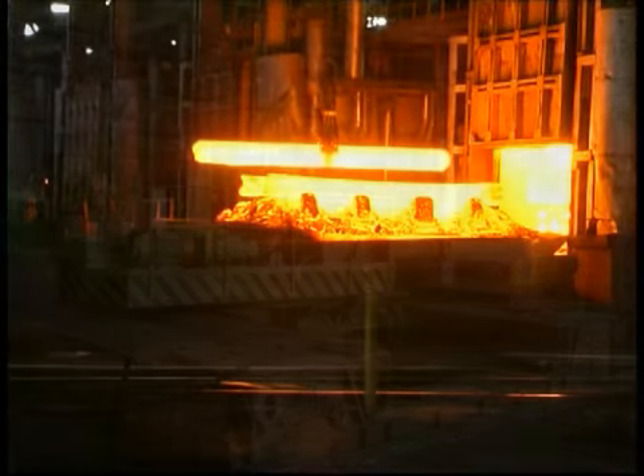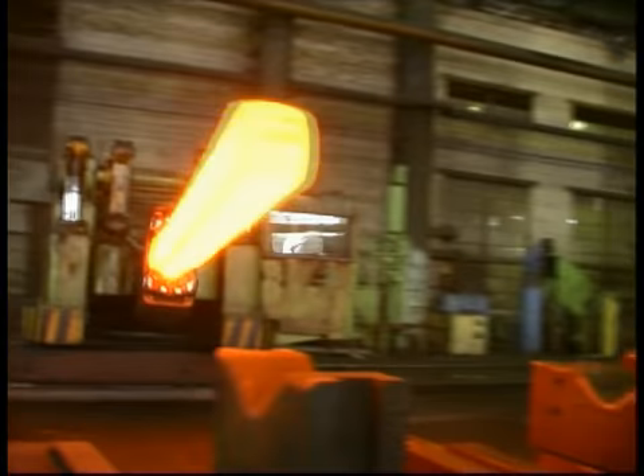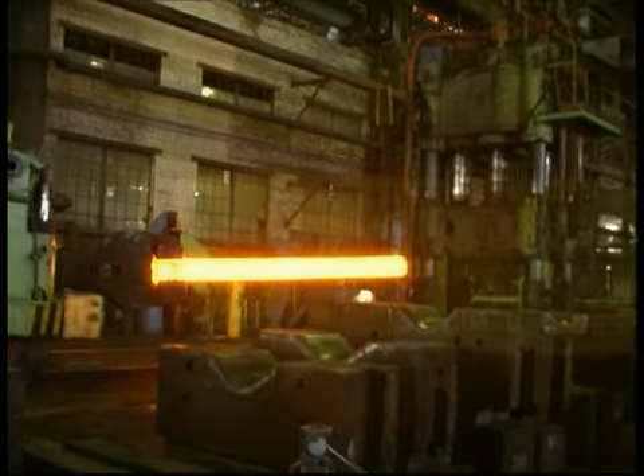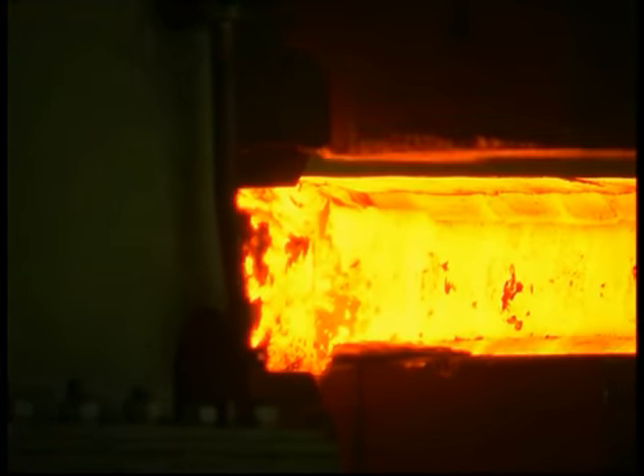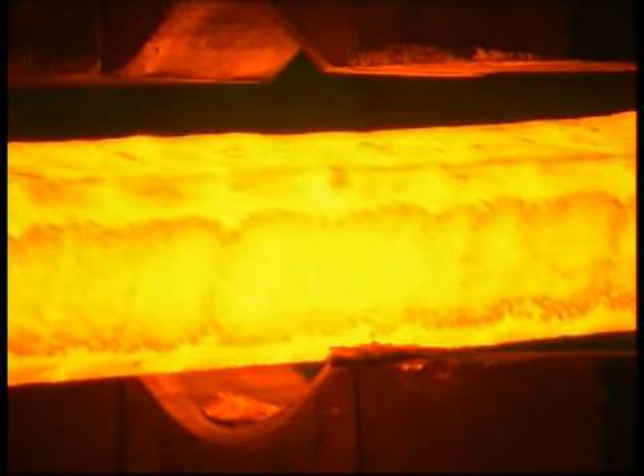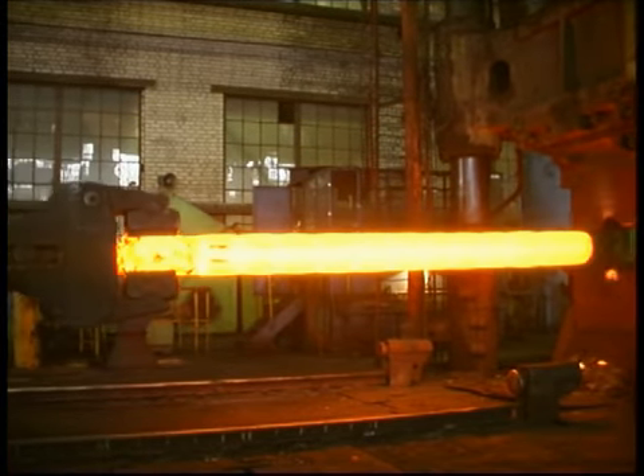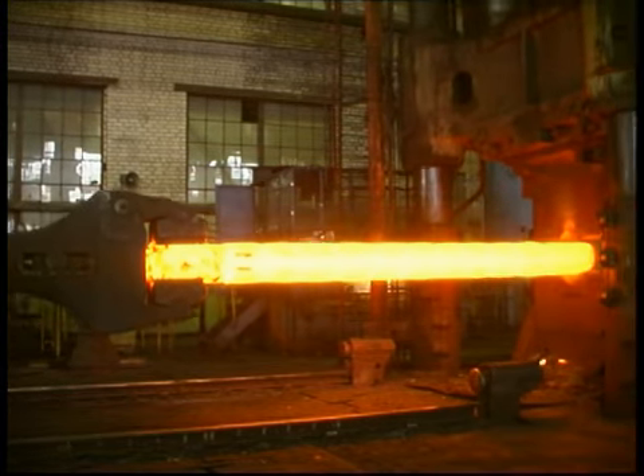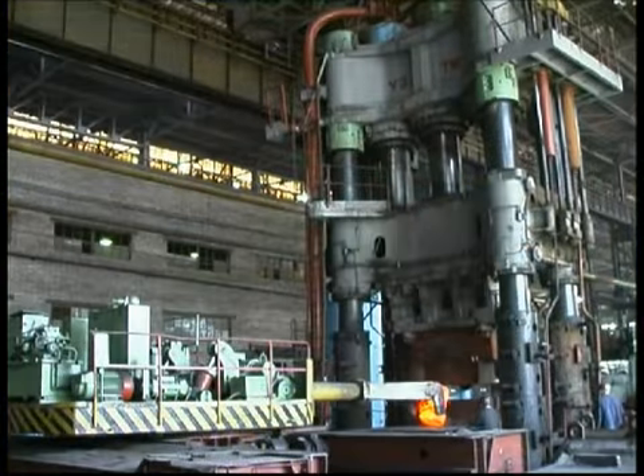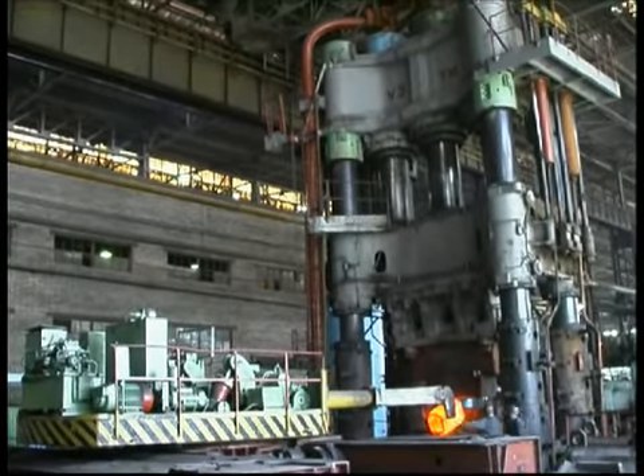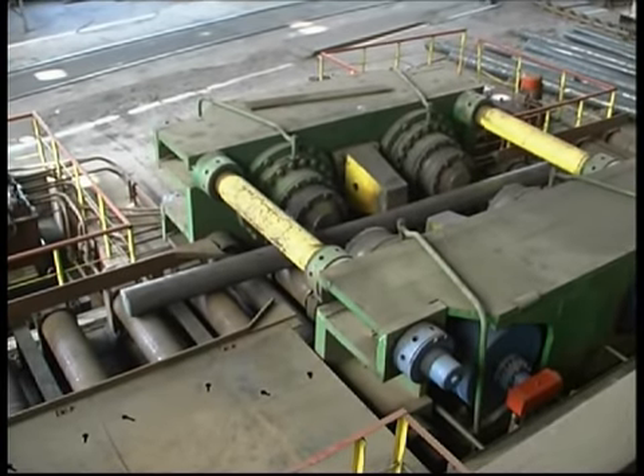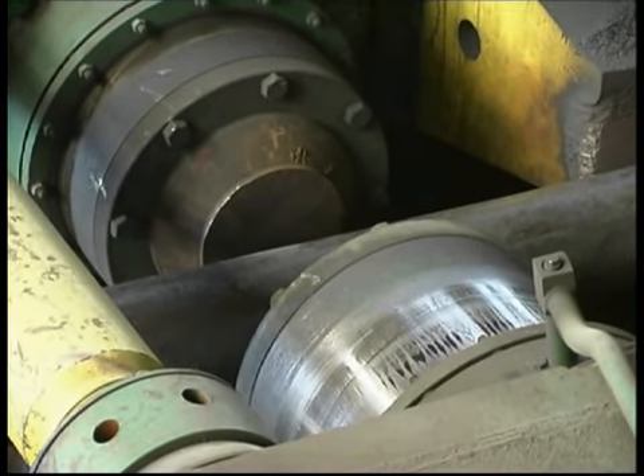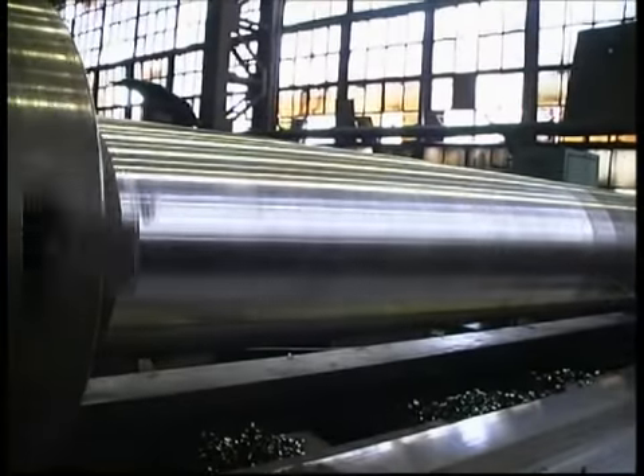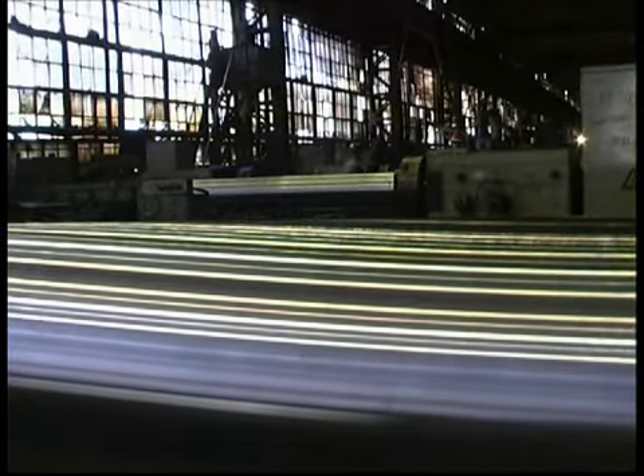The forge and press shop is designed for producing large round and square forgings of 180, 600 and 450 millimeters in section correspondingly, flats up to 300 millimeters in thickness and 800 millimeters in width, and discs 400 to 1100 millimeters in diameter, 120 to 350 millimeters in height. The shop is furnished with hydraulic presses with a capacity of 3,200 and 6,000 tons, manipulators with a capacity of 5 to 10 tons. Forging flattening is performed on unique gag presses designed and maintained by our specialists. Subsequent turning of round forgings and flat cutting ensure high quality of furnished bar surfaces.